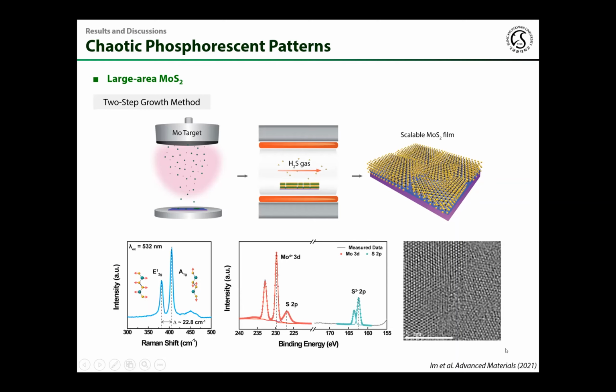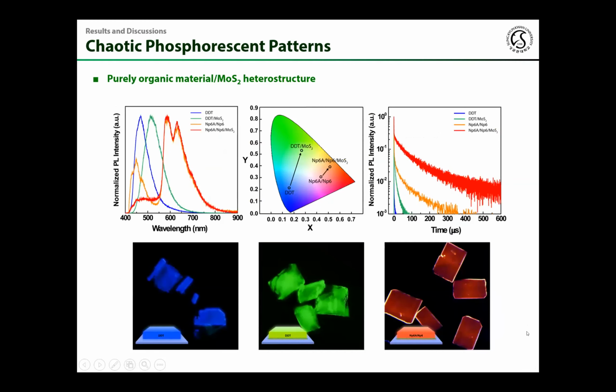Actually, this can achieve high randomness of finer purely organic crystals on the MoS2, because the purely organic material tends to nucleate and crystallize following the lattice structure of the MoS2 basal plane. Based on that atomic seed, I formed the purely organic material and MoS2 heterostructures. As I mentioned earlier, MoS2 can achieve sufficient stabilization of phosphorescence, attributed to crystalline enhancement of purely organic materials.